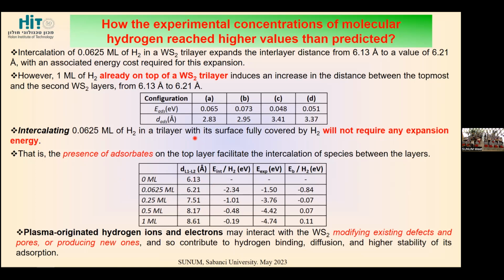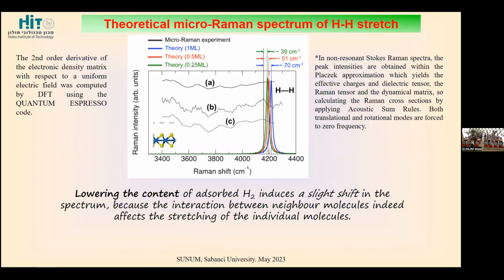So already with the hydrogen absorption, we gained a lot of energy that otherwise we would have to spend on the expansion of this layer. So this process is very beneficial not only for hydrogenation, but also to introduce different species inside the nanoparticles structure without a lot of energy being involved. And we also supported our micro-Raman measurements of this chemical structure with theoretical calculations, and we showed that the peak position is also related to the concentration of hydrogen molecules inside the samples.